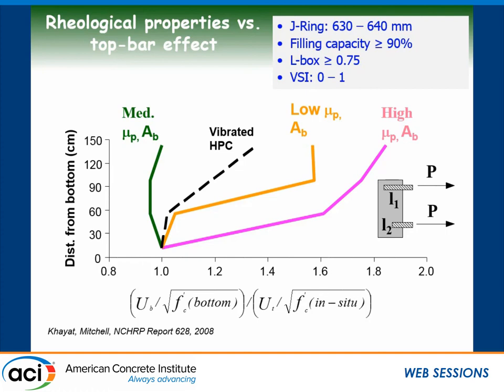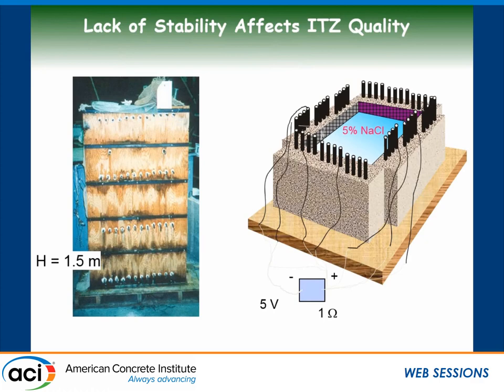But the one, again, that was very surprising is this one. Any guess what happened there? Very, very stable mix, very viscous. What happened is that we entrapped air bubbles. So if the viscosity is so high, you can entrap air bubbles and you don't encapsulate your rebars, and that can affect settlement. Okay, very quickly, the last part is what about transport property?